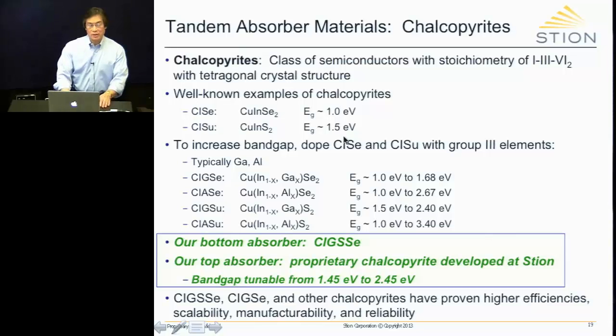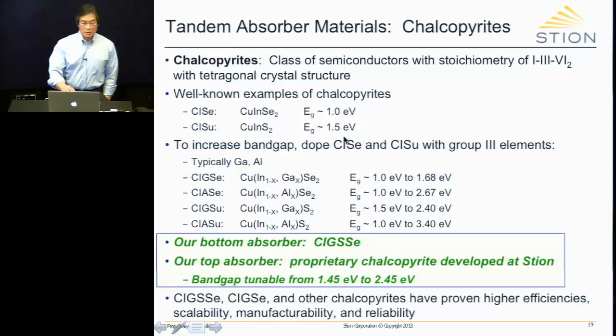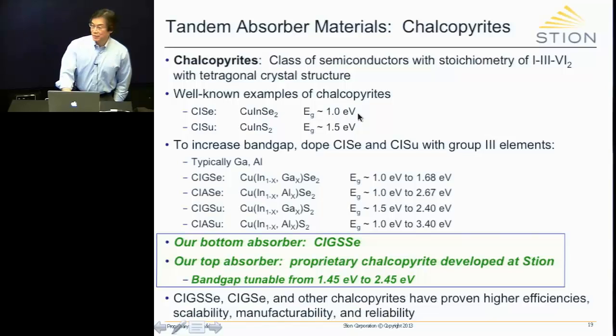If you look at these two and the band gaps, what you would think is that, well, at 1 eV, that's pretty good for the bottom device. 1.5 is just short of what it really needs to be. It needs to be closer to 1.7 eV. But it's also closer to where the Shockley-Queisser limit needs to be for a single junction device. But it's just a little bit high. So it's sort of in this limbo land for where copper indium disulfide needs to be. So how do we change that? How do we move this up to 1.7 or greater? Well, one way to do this, and these are efforts that other people have done.